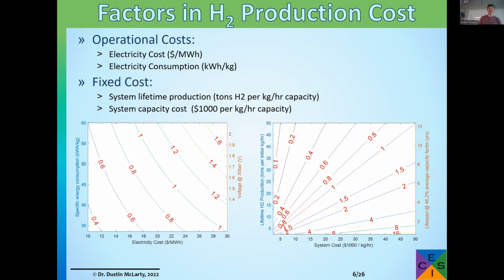The right graph is focused on your fixed costs. I put on the bottom axis the cost per kilogram hour of capacity, and on the vertical axis, how many tons of hydrogen over the lifetime of that system. And then I tried to make the right-hand axis just a translation to something easier to understand. So if we're talking about trying to get to this $1 per kilogram target, we probably want to be somewhere on the 80-cent line, which means we need to be around 45 kilowatt hours per kilogram. And that translates to operating an electrolyzer somewhere around 1.5 volts.